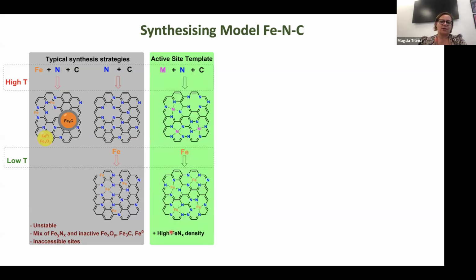You have a zoo of active sites, some single metals, but also a lot of others. Another approach is to first just dope the carbon with nitrogen, and then try to throw in the iron that would be coordinated to nitrogen. But this is also quite difficult, and you get an unstable mixture of iron nitride, iron oxide, iron carbide, and a lot of these iron sites are not accessible.